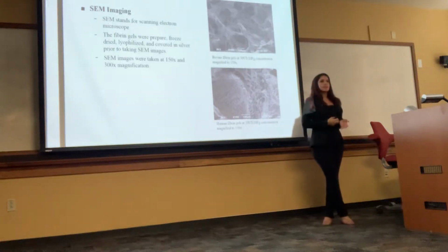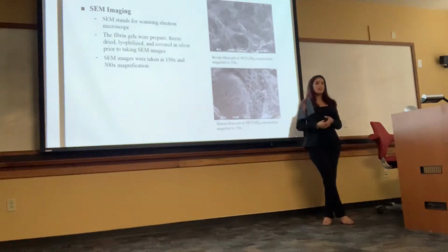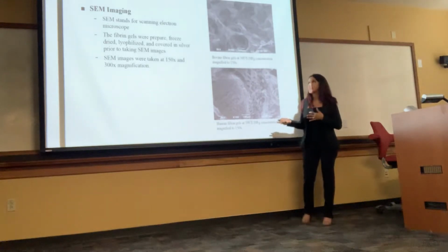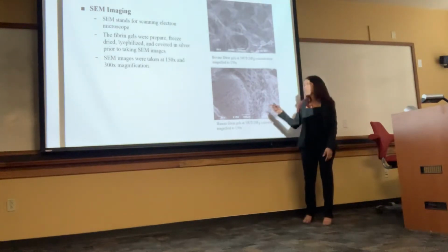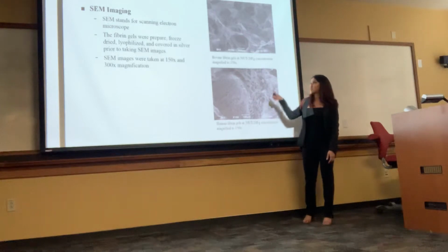For the SEM imaging, we prepared the gels, freeze-dried them, lyophilized them, and coated them in silver prior to taking these images. We took two different magnifications, 150 and 300.